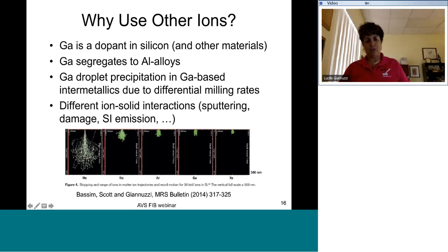These are Monte Carlo calculations showing ion trajectories and the recoil interactions. You can see that we've got helium, neon, argon, gallium, and xenon. And as we go to heavier and heavier ions, this is all in silicon at 30 keV, you can see that the heavier ions are stuck closer to the surface, and this is all at normal incidence. So the ions are coming in perpendicular to the sample surface.